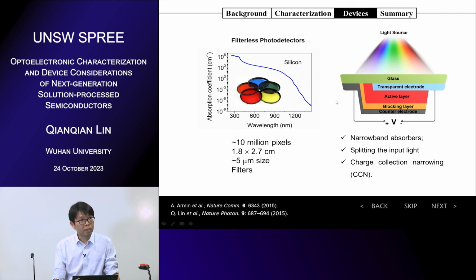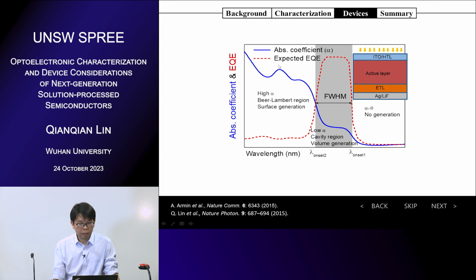How to design narrow band photodetectors. So we use perovskite, from early years, because perovskite has tunable optical constants or optical absorption spectra. If you have a high absorption coefficient at a short wavelength, and a very low absorption coefficient at a long wavelength region, the carrier generation will be quite different. For high alpha, you will get surface generation because most of the carriers are absorbed just in front of the ITO electrode, not in front of the active layer. So it's very close to the ITO electrode.